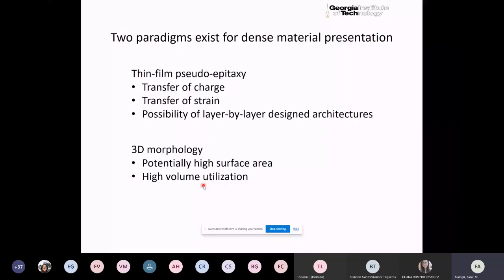So from a study point of view, it seemed very intuitive for us to go to two-dimensional catalysts. That is, if we could make sure that the catalysts are at least flat, then we can study the effect of, let's say, one of the dimensions. Just by making the catalyst thicker, we could try to see how the number of layers of the catalyst affects the activity. Because the larger the number of layers, the further the surface layer is from the substrate. So that's one effect.